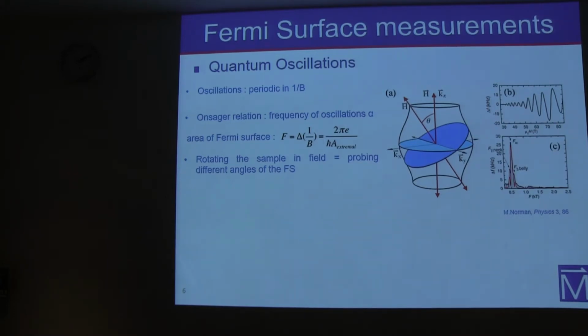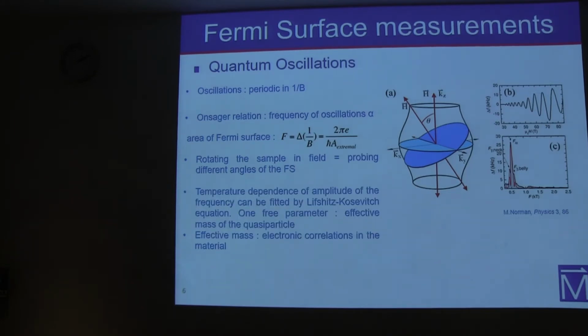Then what can we do? By rotating the sample with respect to the field, we can probe all of the various areas of that Fermi surface. So by rotating the field, we get the shape of the Fermi surface in all directions. This is at base temperature, and by increasing the temperature, so by looking at the temperature dependence of the amplitude of those oscillations, we can actually fit.